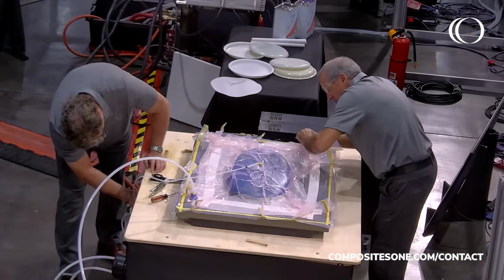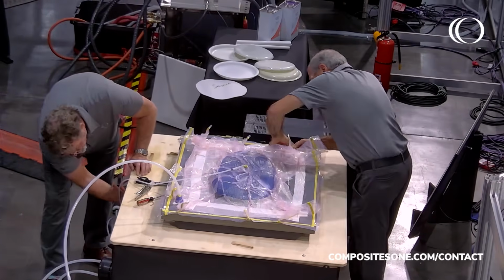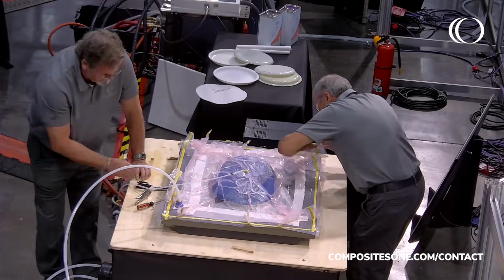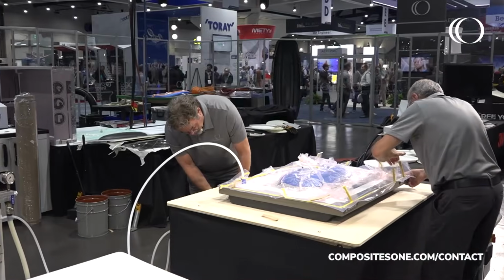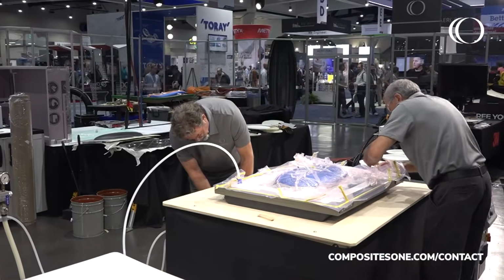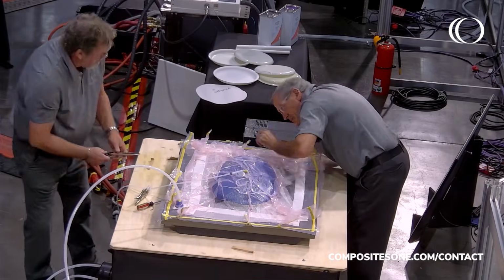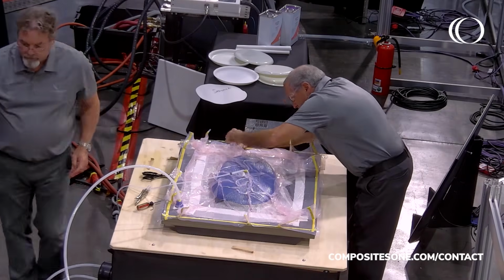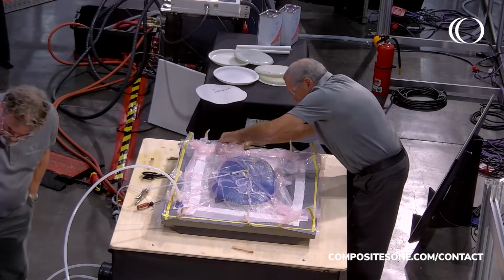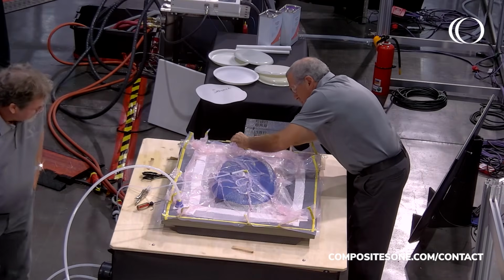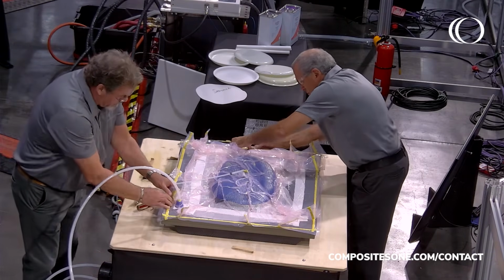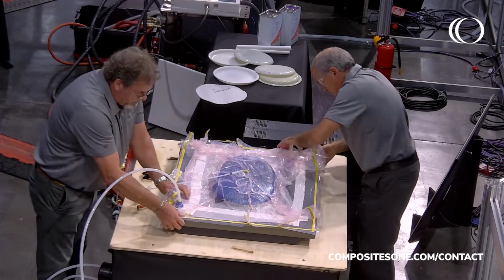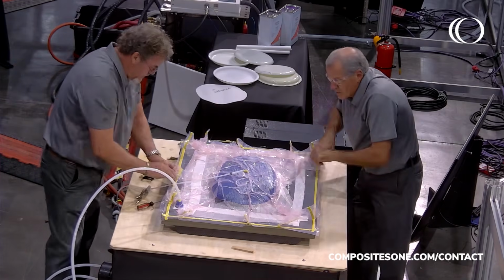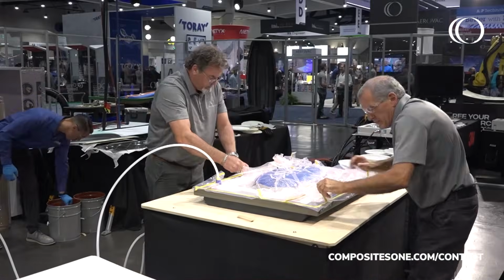So now Barry and Dan are just doing their final leak checks on all the pleats. In the vacuum infusion process, you need a leak-free bag, and so they're going around just making sure there are no leaks in the pleats. That's where they would tend to occur in the sealant tape, and just do a final leak check before we start the infusion process.